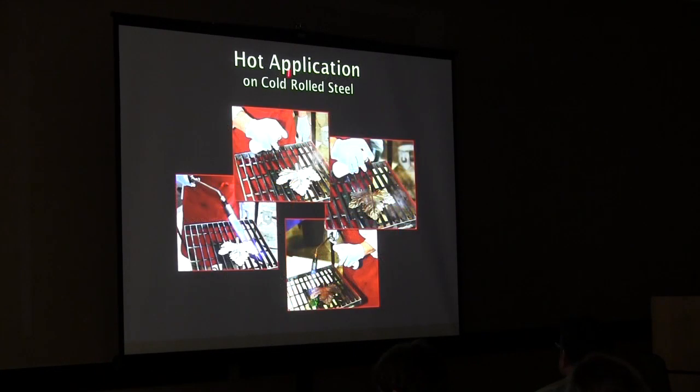Here again, blue flame, real important. Okay, I'm heating up this sandblasted piece. And this is Japanese brown put on hot. You can put it on cold and you get orange browns. If you put it on hot, you get these burgundy blacks. So I'm heating it up here. You can see it's starting to work. And right over in this corner here is what it's going to look like.